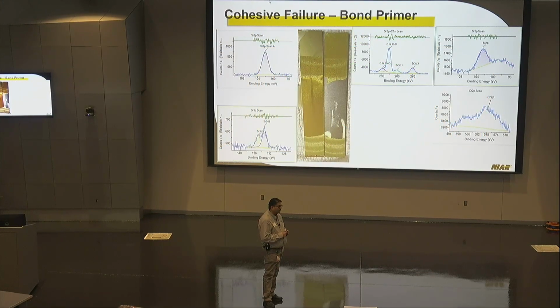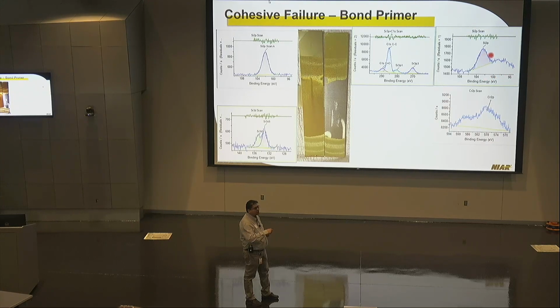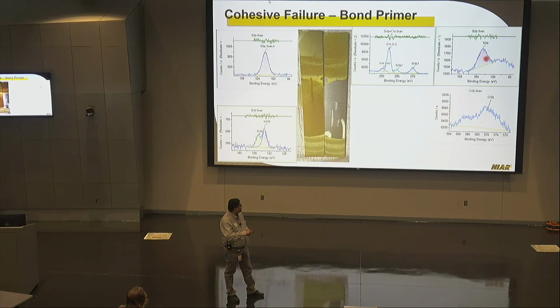Okay. Because the metal itself is 2024, it has also silicon inside. I asked the president, are we sure that it's organic silicon? So the organic silicon signal is basically at 102. If you have a silicon metal, that will be in. Yeah, see out here, we are seeing slight elevation. So that would be your silicon metal. Tim, what is the silicon metal peak energy again, binding energy? Okay. So probably that is why we are seeing a slight hump in here, that might be the silicon metal itself. But this particular peak is definitely organic silicon.